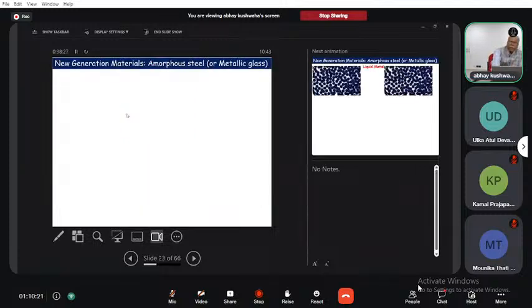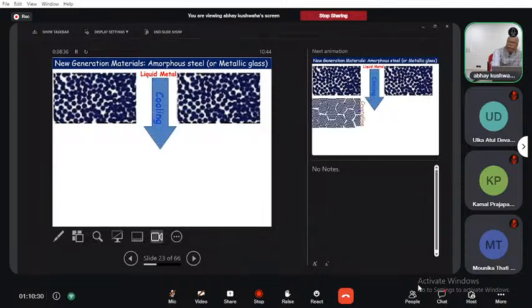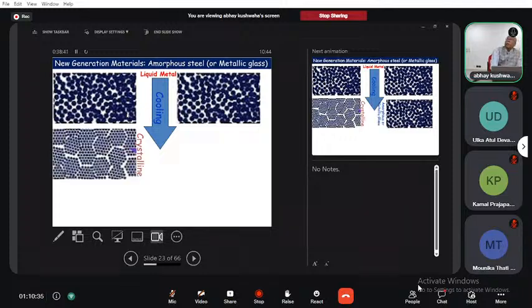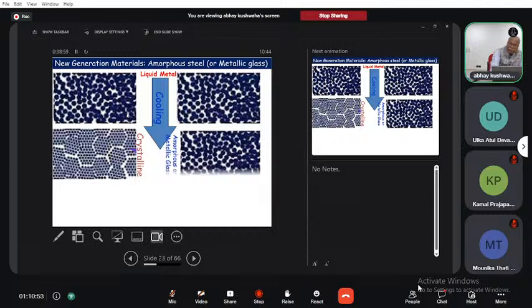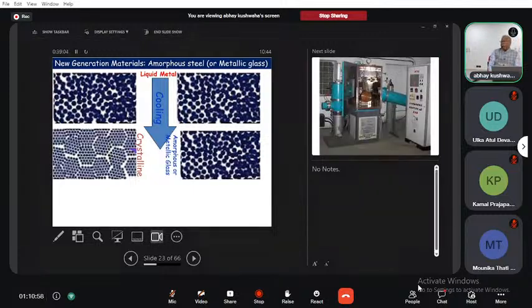Now, how does the crystal structure come? If we melt a material and give sufficient time during cooling, an equilibrium structure comes, and a crystalline structure is an equilibrium structure. But instead of giving sufficient time, if we quench the material from the liquid state to a solid state, retaining the liquid structure as it is, then I can eliminate the magnetocrystalline anisotropy of that material. This is basically the philosophy of going for the amorphous material. Why are we going for amorphous material, amorphous steel or metallic glass, whatever you call it? Because this is a glassy structure. It does not have any crystalline anisotropy.